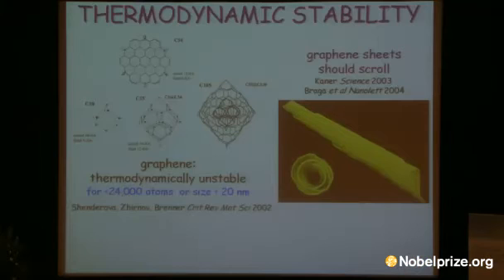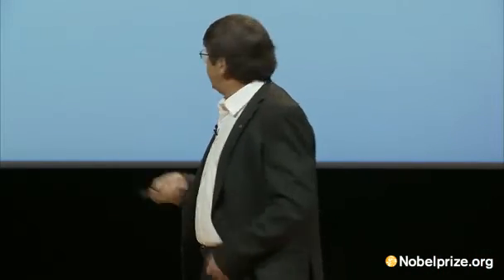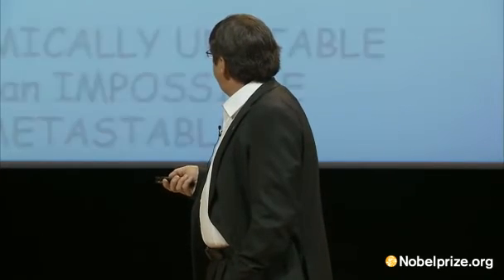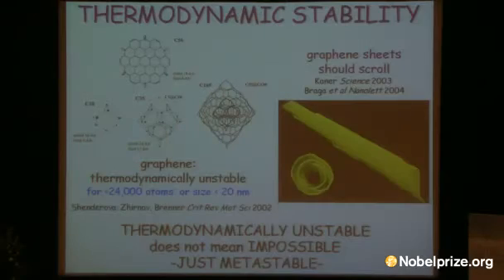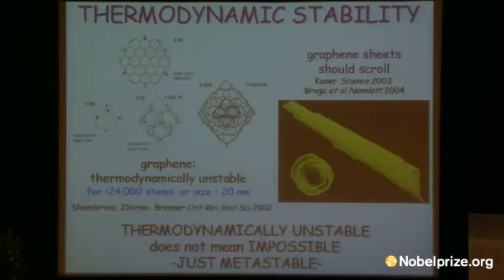Even if you grow a large crystal, simple thermodynamic arguments tell you that a graphene sheet is not stable, it should scroll up. All those arguments remain valid today as well, and the only reason graphene exists is the same reason diamond exists. It's less thermodynamically stable than graphite under ambient conditions. So we're dealing with a system which is metastable, but it's still possible.